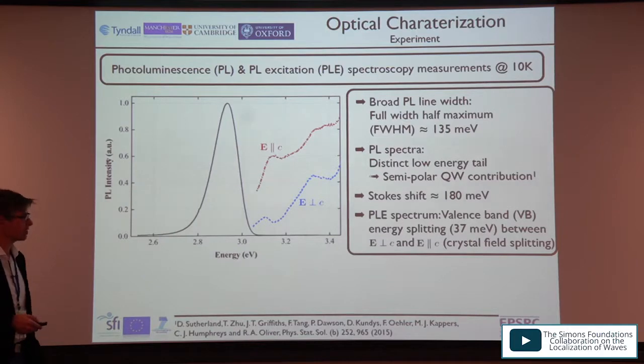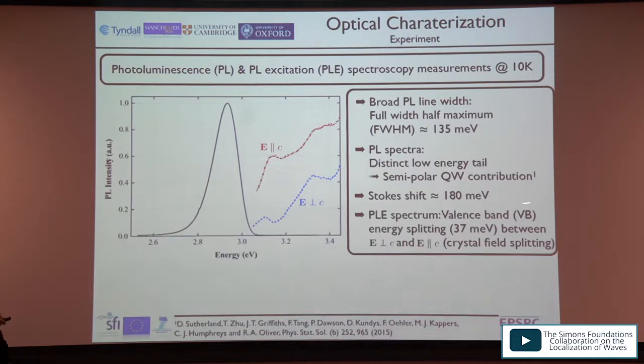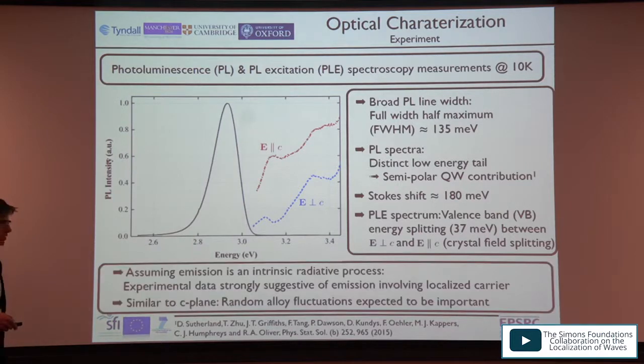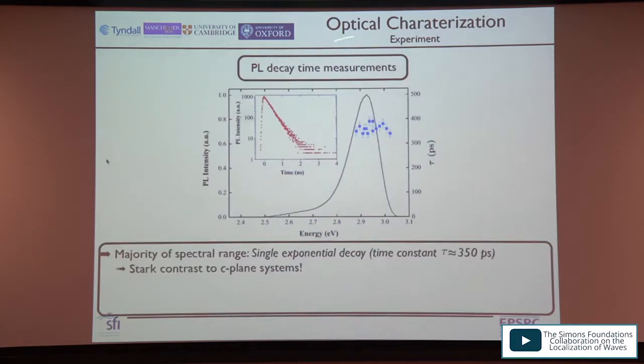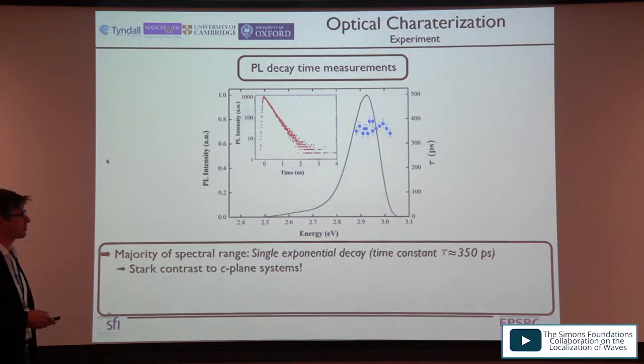The PL spectrum of this M-plane system shows a PL peak with two light polarization components from PLE measurements corresponding to the two valence subbands. The PL linewidth is very broad at 135 meV, with a semi-polar contribution on the low-energy side. The Stokes shift is 180 meV, which is massive. The PLE splitting gives insight into valence band splitting between polarization components perpendicular and parallel to C. This strongly suggests involvement of localized carriers, similar to the C-plane system.